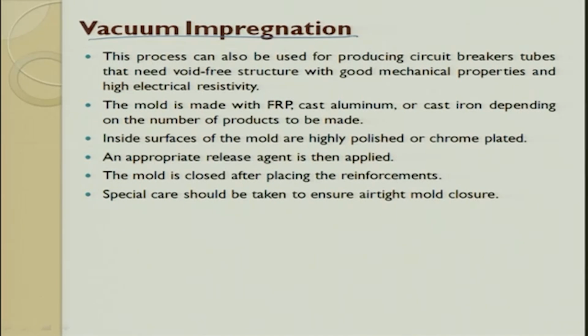The process is used for, these are examples I have given, producing circuit breaker tubes that need void free structures with good mechanical properties, which are always done by vacuum impregnation molding. Here the mold is made out of FRP or cast iron or cast aluminium, depending upon the product you make. The inner surface of the mold is highly polished to give a smooth surface, and a releasing agent is also applied. The mold is closed after placing the reinforcement, and the vacuum is applied, then the resin is sucked inside.